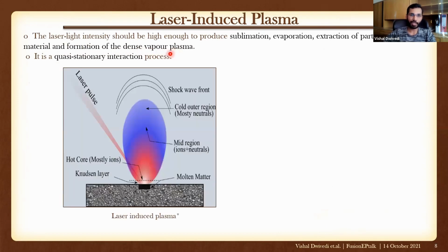For LIBS, the laser light intensity should be high enough to produce sublimation, evaporation, extraction of particles from the material, and formation of the dense vapor plasma. This is a quasi-stationary interaction process, and this is a LIBS plasma image. We can see in the hot core mostly ions, the mid region contains both ions and neutrals, and the cold outer region is mostly neutrals. After that there is a shock wave, and here is the molten matter.